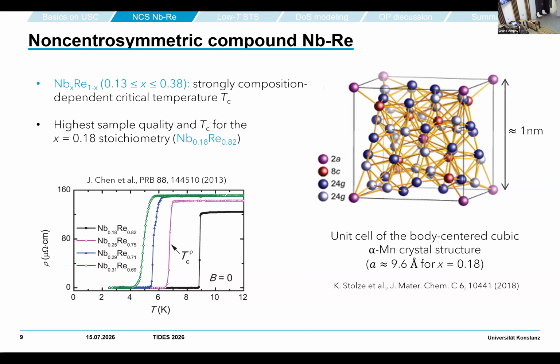Depending on the stoichiometry, the superconducting transition temperature changes. This is shown here with resistivity measurements as a function of temperature for different compounds. The one shown in black is the one with 18% niobium, exactly the stoichiometric compound we are investigating, which has the sharpest transition and also the highest TC.